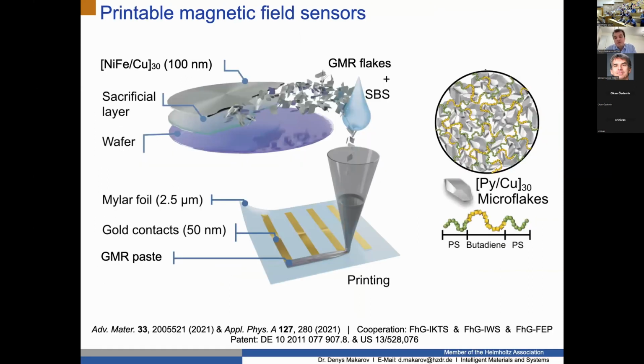The idea behind it is very interesting, especially for material scientists, because here you have to really apply all the knowledge about materials and the composites and percolation effects, electrical percolation, mechanical stability of those composites. Imagine you have somehow a powder, which is magnetosensitive, can be thin film fabricated GMR flakes, or you simply buy or fabricate magnetic particles. You put them in a binder.